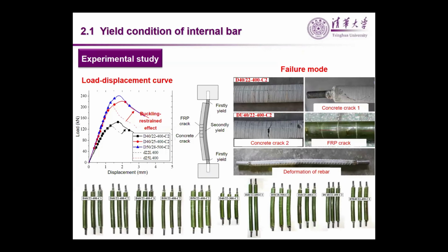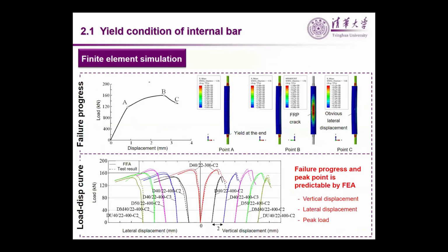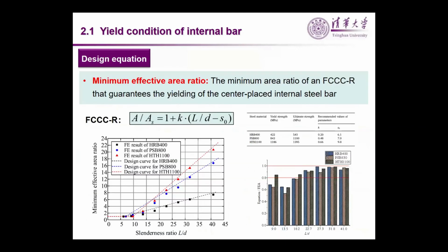And based on the experiment, the finite element model is then established by using software ABAQUS. The failure progress and the load displacement curve of the specimen obtained from the FE model agree well with the test result, and additional parameter studies were also carried out. And finally, based on the criterion of the rebar yielding, the basic configuration rules of the FCCC-R are proposed. As long as the FCCC-R meets the requirement of the proposed minimum effective area ratio, the yield of the embedded rebar under compression can be ensured.